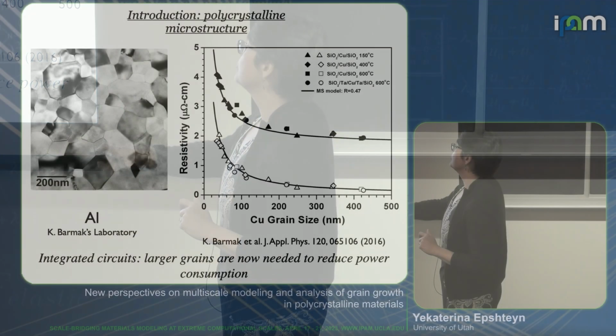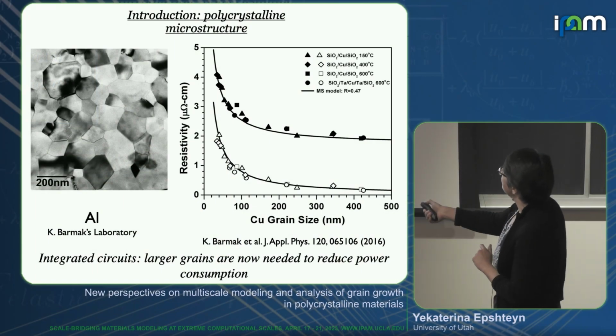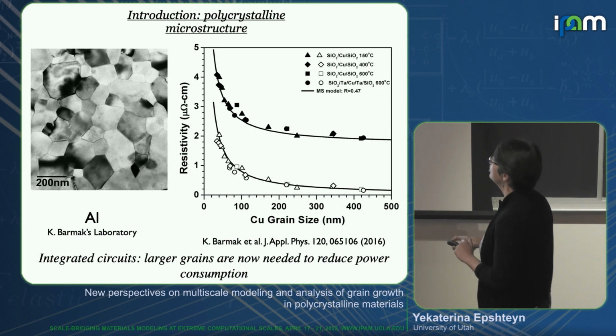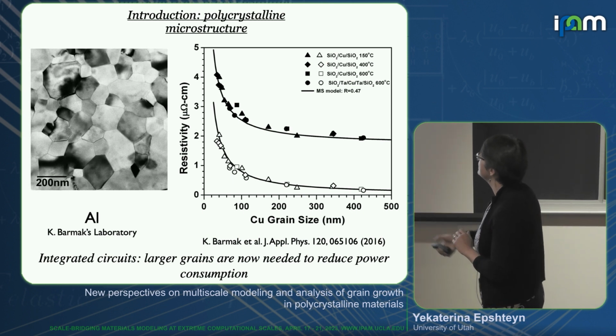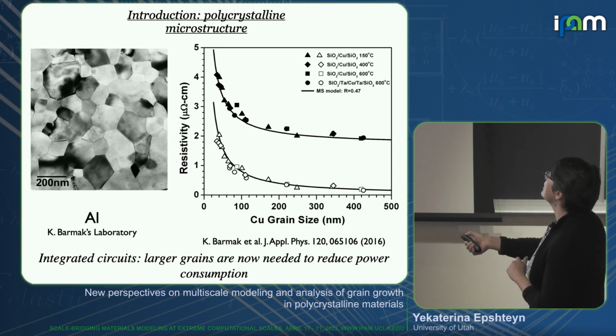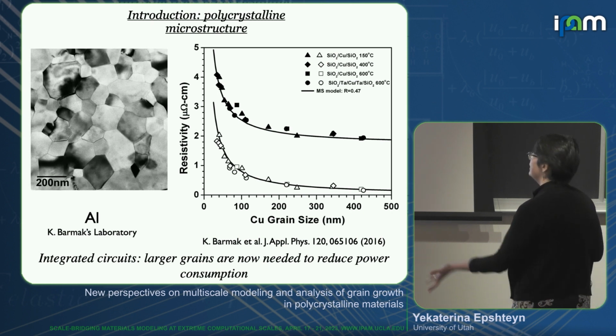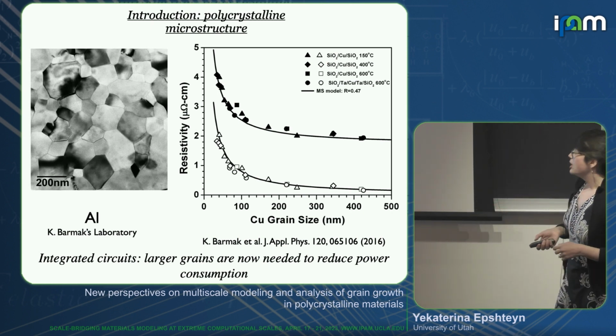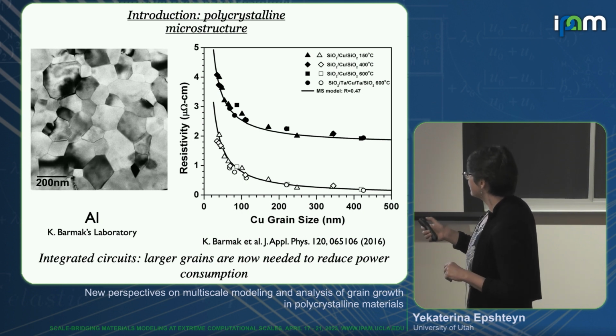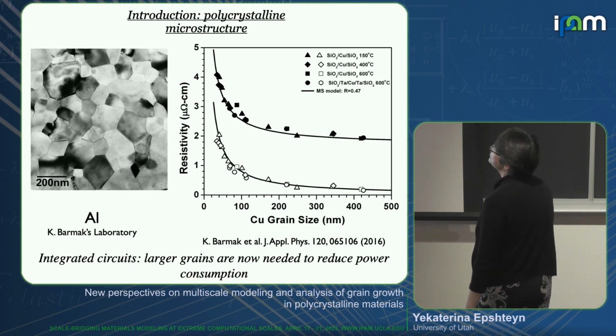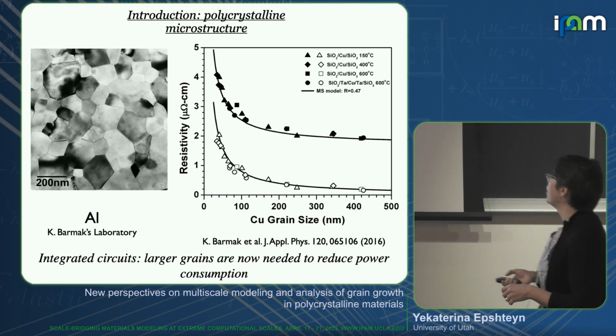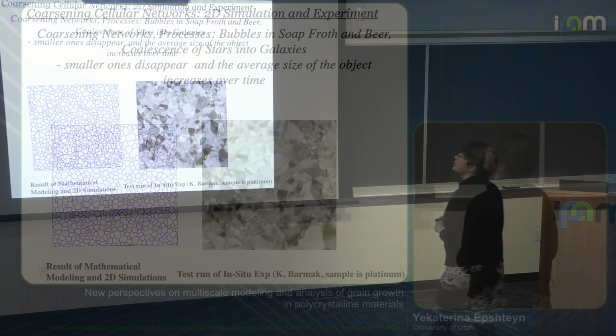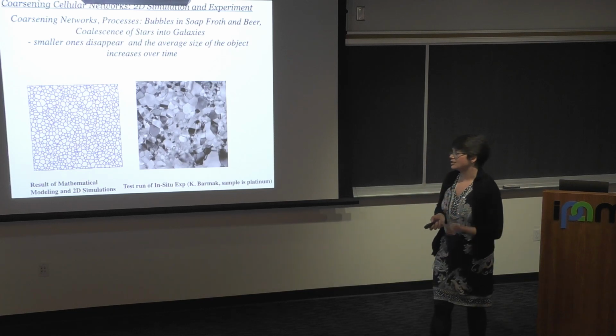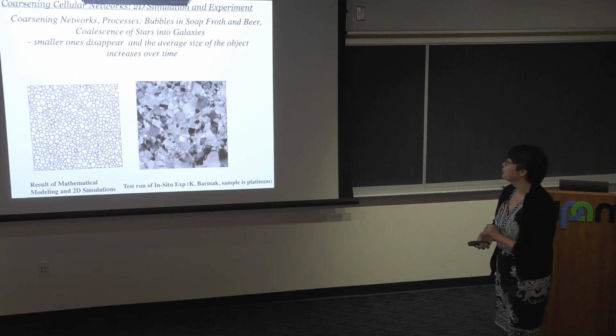So here is an example of an aluminum thin film, and here are results that show that, for example, electrical resistivity in copper decreases with grain size. So for example, if we want to reduce power consumption, maybe we want to develop materials that on the microstructural level have larger grains. Of course, different applications might demand different microstructural properties. So there is the important question of how we can change microstructural properties and in turn also affect material properties.